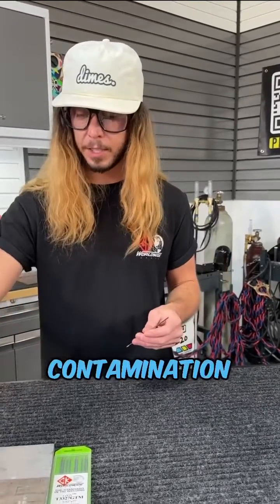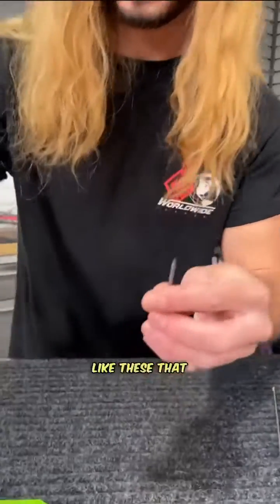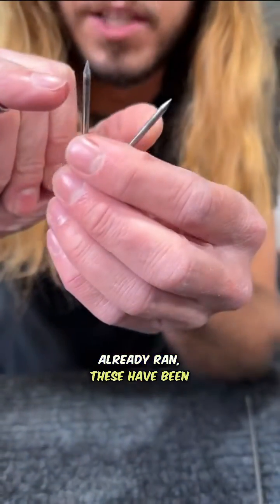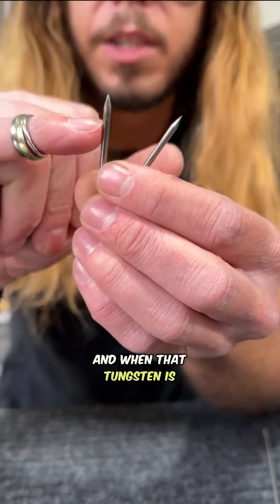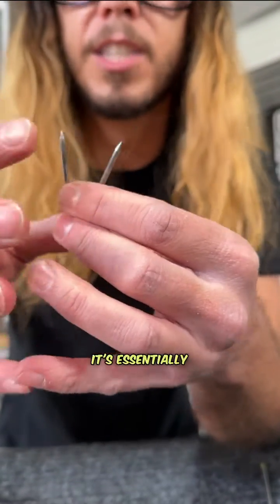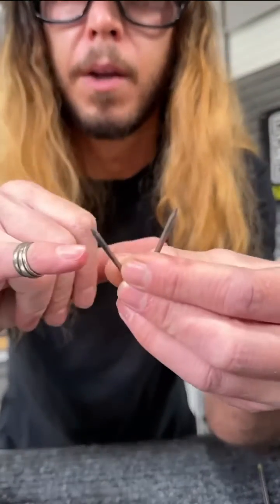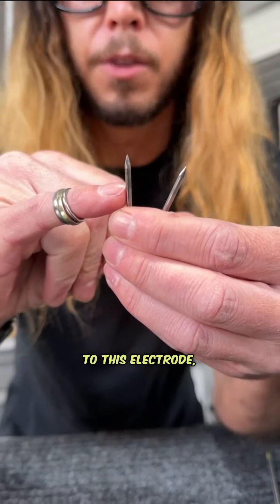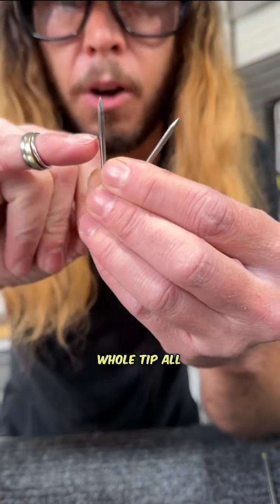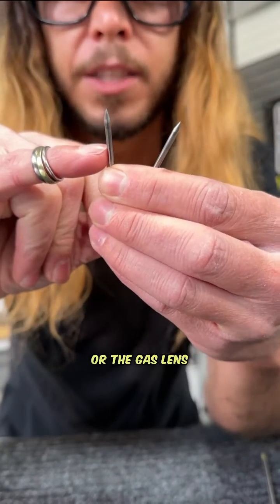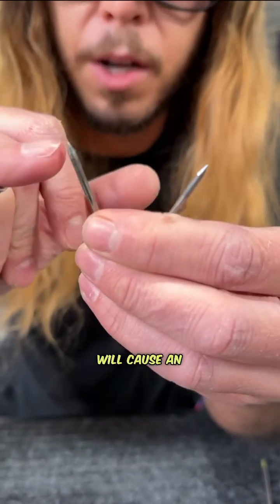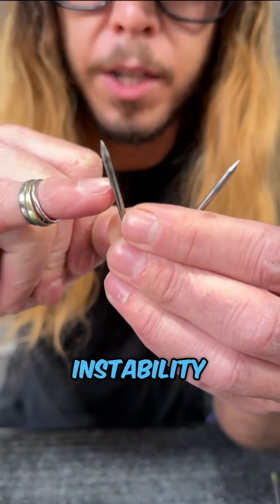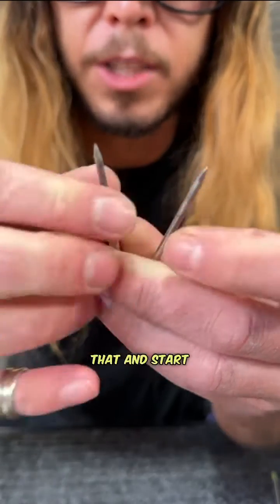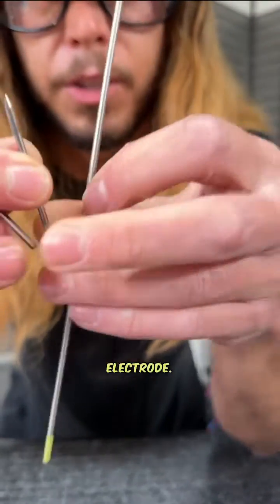If any contamination has been introduced to the electrode, like these that I've already run, these have been contaminated. When that tungsten is glowing red and it's essentially porous, that grain structure opens up. If any foreign metal is introduced to this electrode, it alloys that whole tip all the way down to where it meets the collet or the gas lens inside the cup. All of that contamination will cause an erratic arc and instability in the arc. So we want to remove all of that and start over with a fresh, clean piece of electrode.